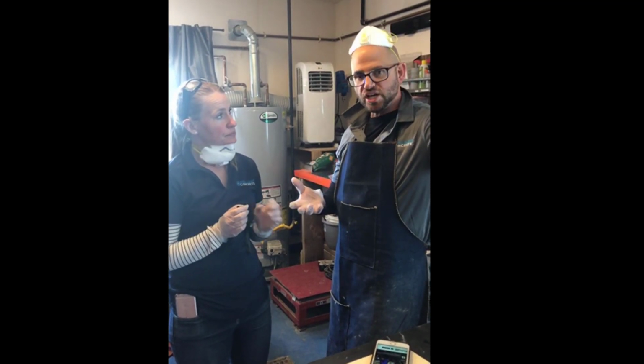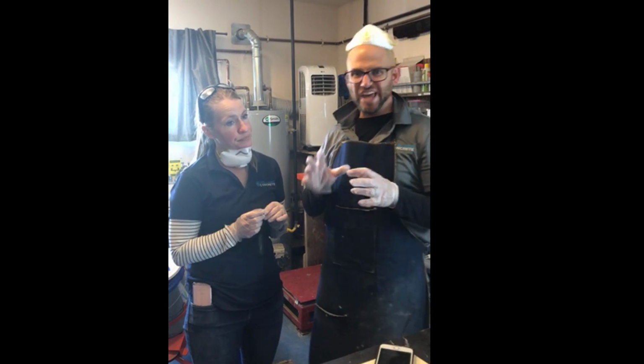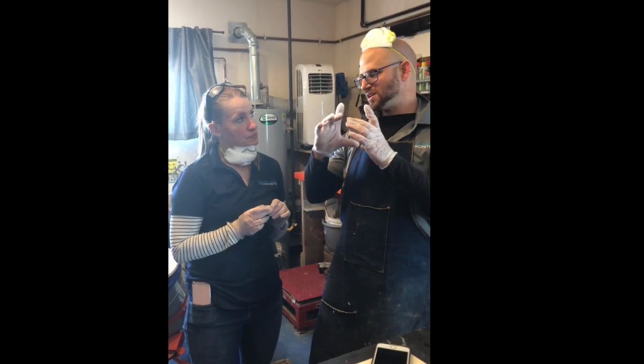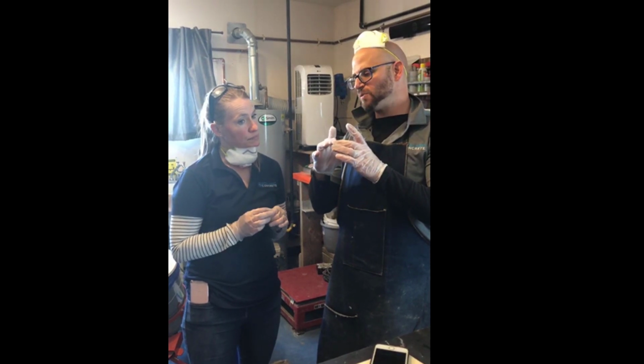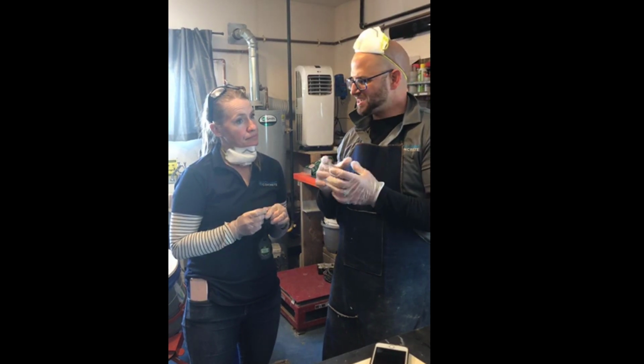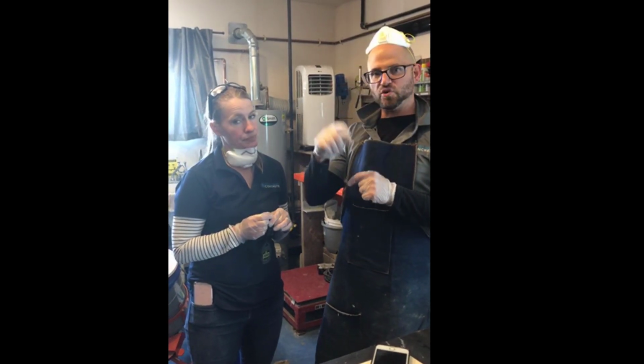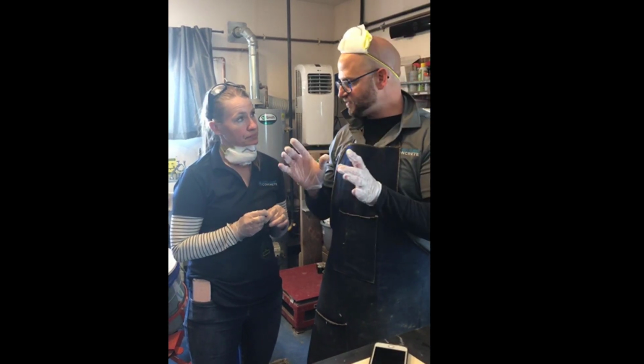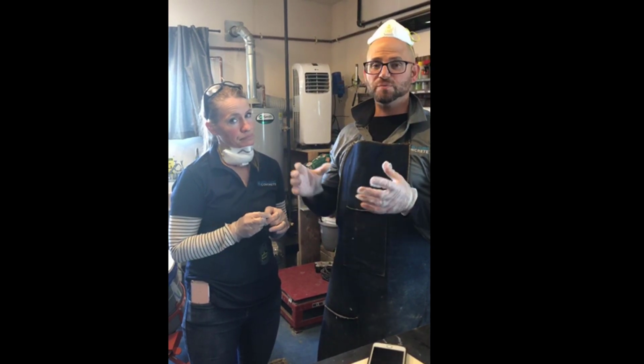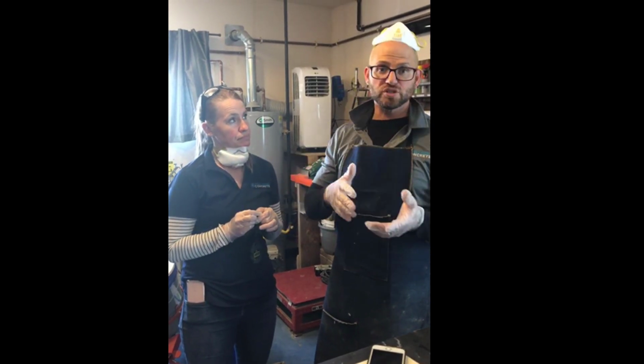The way we changed it is we put two different types of crack in there. Either cracks that you can't see, which are fatigue cracks, where we put our sample, a 2 or 3 inch diameter puck that's 2 inches tall, into our compressor machine as if we were doing a split tensile, cut it on either end, and really create the localized event for crack elongation. So we crack it first, all the way full, to find out where it's going to fail. We do that for 3 samples and we put them back together, and then we do fatigue cracks. And then we have a virgin sample that has no cracks.